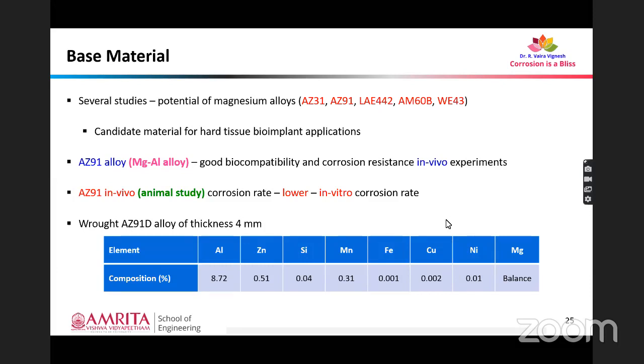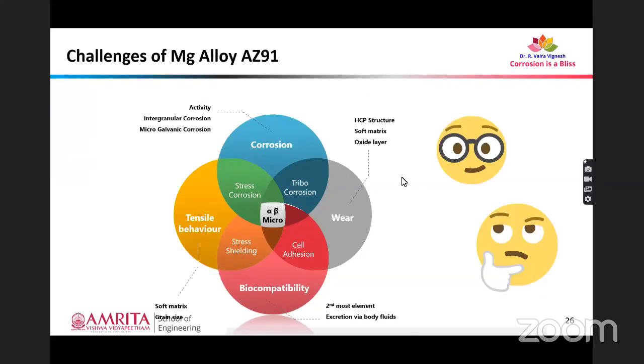So in this study, we have taken wrought alloy AZ91 of thickness 4 mm, whose composition is shown over here, as our base material, and then we have conducted experiments. Coming to this magnesium alloy AZ91, it has two phases: alpha phase and beta phase. Alpha phase is the primary phase of the alloy, that is alpha magnesium, and beta phase is an intermetallic phase between magnesium and aluminum. So these phases influence all the properties of the material.